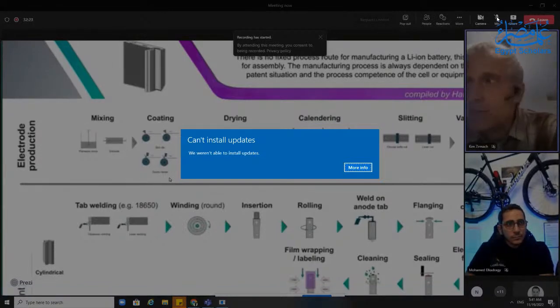See, primarily graphite, a conductive agent, and a binder, aka the glue. The standard glue in an anode, and again, always exceptions to this, are carboxymethylcellulose and styrene butadiene, a low molecular rubber. Why two different glues? Well, it turns out that one of them, the CMC, is good at cohesion, which is gluing the graphite to the graphite, and the SBR, the styrene butadiene, is good at adhesion, gluing that whole thing to the foil. It's the anode to the copper foil.